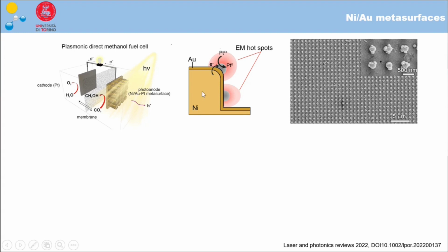What we did is to use always the same self-standing nickel pillars arrays and films, which is on the order of centimeter scale, covered with gold to enhance the optical properties, like an ultra-thin layer of gold made by 10 to 30 nanometer of gold. And then with photo deposition, we use the electromagnetic hotspots to photochemically deposit the platinum nanoparticles, which are the catalysts for methanol oxidation, selectively only on the electromagnetic hotspots. As you can see here, and also in the SEM image, we don't deposit the catalyst on the flat surface, but mostly and mainly where the electromagnetic fields are higher.